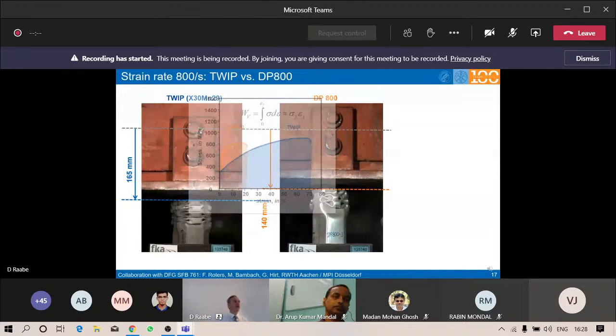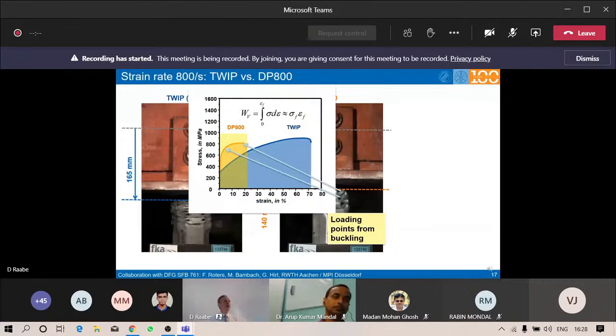But when you look a little bit closer and you look at some of the strained points, particularly here from the highly strained parts and the buckling area of these crash boxes, and translate them back into these simple stress strain curves, then you can see that the maximum strain does not exceed 18 or 20% maximum. And that means the high strength in this area means that only this part of the total integral is really needed for designing such a part. So the very high energy absorption capability of this TWIP steel as a counter example is actually not really needed for this specific design of such an automotive crash box as shown here.